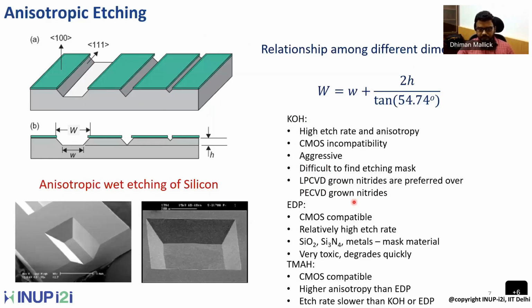Then EDP is the other agent. That also has a very high etch rate, but it is not typically preferred because of its toxic nature, and it also degrades quite quickly. The third one is tetramethyl ammonium hydroxide. That is quite highly preferred for this kind of silicon wet etching because of its high anisotropy when compared with EDP, but at the same time it is not as aggressive as KOH, so its etch rate is slower than KOH etching.